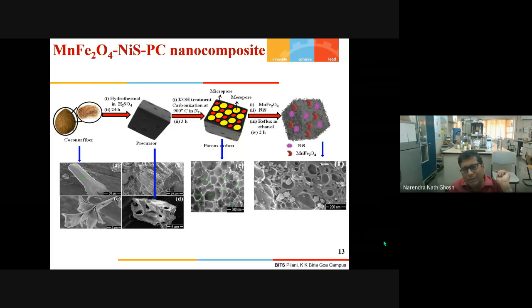Separately, we have made the manganese ferrite and nickel sulfide. Then, by using an ethanol reflux method, we incorporated those nanoparticles on the surface as well as in the pores of the porous carbon. You can see that here, the nanoparticles are immobilized within the pores.